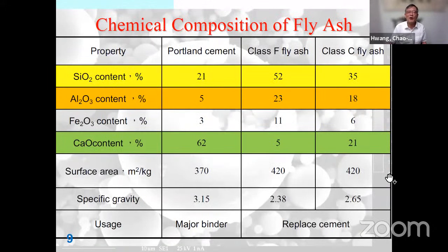By looking at the chemical composition of fly ash compared with cement, Portland cement, class F fly ash actually contains less CaO, or calcium oxide, and class C fly ash contains a large amount of CaO. So class C is more reactive, but that is a little bit harmful to durability. As compared with cement,